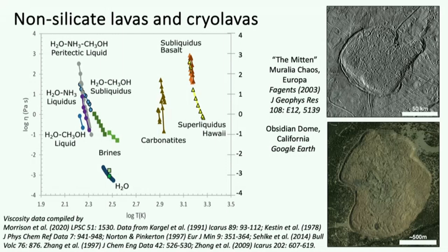So, log viscosity, inverse temperature. Sorry, I thought I'd put the real temperature on there in a way we could read it, but I didn't. Never mind. Right, basalts. So here we've got Hawaii lavas in our viscometer above the liquidus, and then below the liquidus as they start to crystallize. Carbonatites are actually more fluid, but not that much more fluid, a factor of 10 to 100 maybe. These are brines. This is water-methanol, water-ammonia, water-methanol-ammonia. And the reason people like to stick methanol and ammonia in their cryo lava is it massively reduces the eutectic temperature and the freezing point.